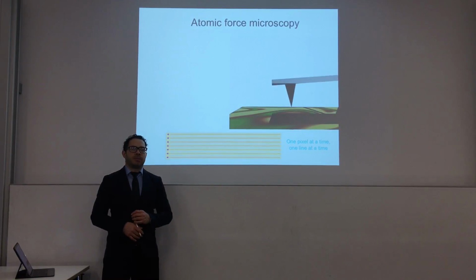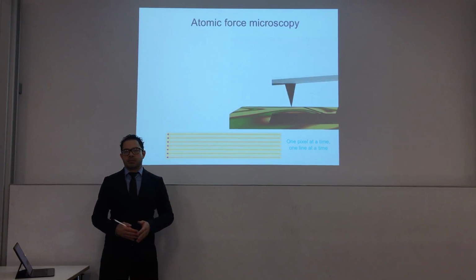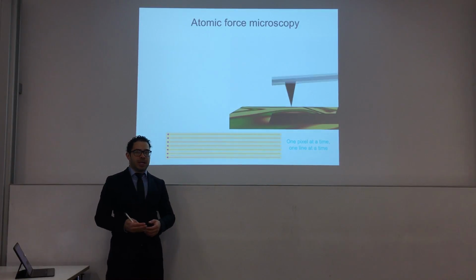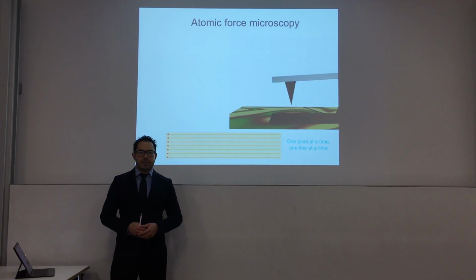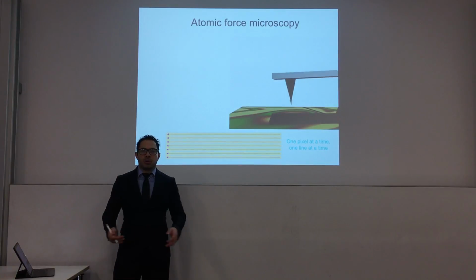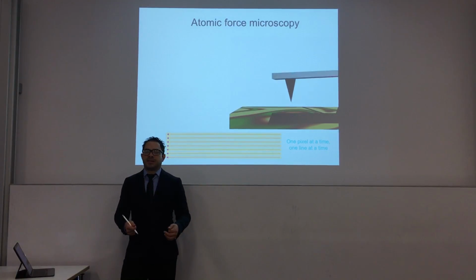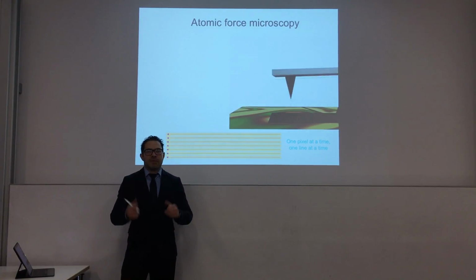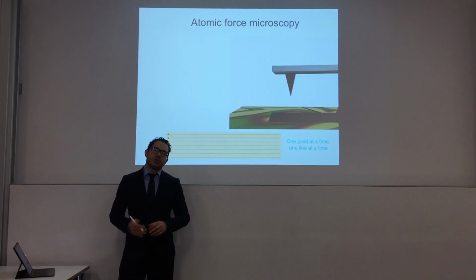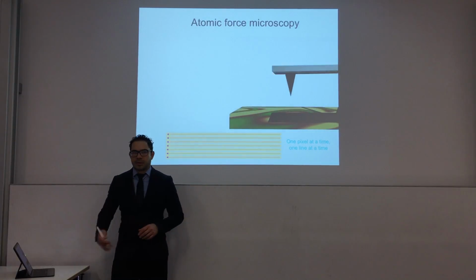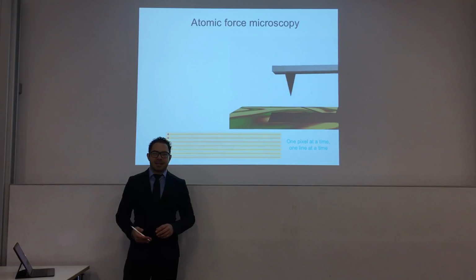The first time I witnessed how AFM worked, I saw it by myself. I was kind of disappointed because I had read about it, but something that people didn't mention is how long it can take to obtain an image. I mean, if you have an optical microscope, you just take your sample, put it on the stage, focus, and you have your image at once. In atomic force microscope, it's not so fast. You require some minutes depending on the pixel size that you have and depending on the scanning speed that you can go.